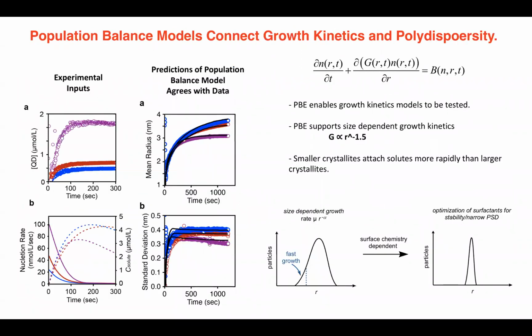So I'm not going to get into this, but it turns out you can relate the polydispersity of the sample, and you can basically model these curves to extract a size and a growth rate on a per particle basis, as a function of size. And so this modeling allows you to see that there are conditions where, with a broad distribution, you'll get size distribution focusing. And you need that to explain the polydispersity, like I said, right?